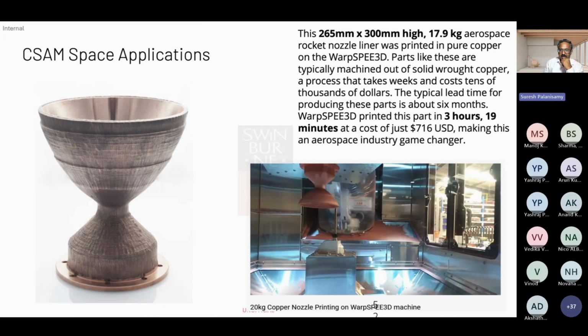And again, a multi-material application. In this case, you can see a pure copper liner is being used. Sometimes multi-material can be done, where the inner layer can be different and the outer layer can be different. In this case, copper is being used here, and the printing time is 3 hours 19 minutes.